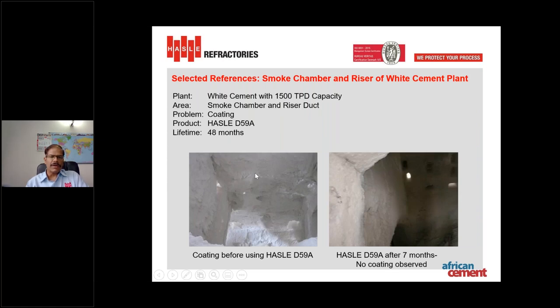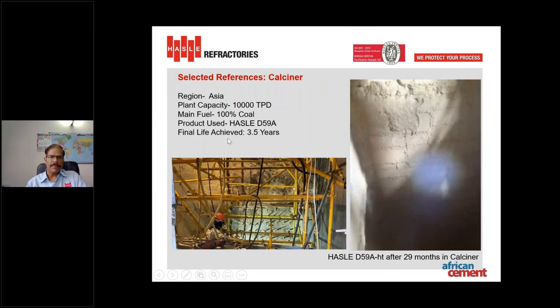This is a case story from one of the white cement plants in Malaysia with a line capacity of 1500. They were facing a lot of coating issues in the smoke chamber and riser duct area. After a detailed study, we supplied and installed our HASLE D59A castable. You can see this picture after 7 months, where no coating can be seen in the smoke chamber area. The total life achieved by installing this HASLE D59A castable was 48 months in this plant.